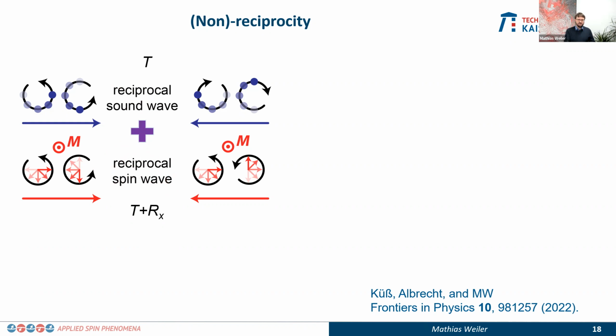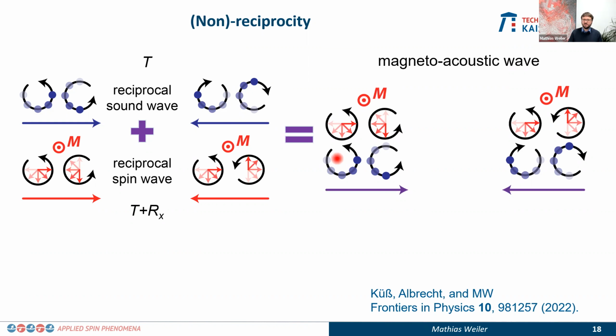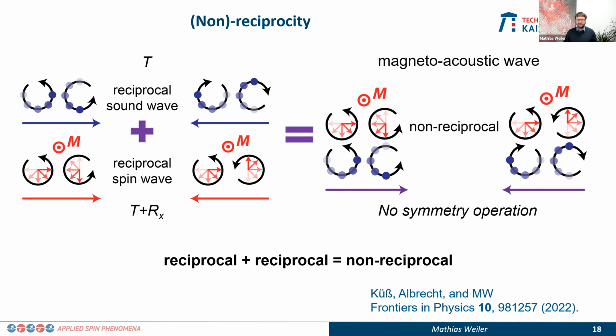But this reciprocity of these two waves, to go from counter-propagating waves to each other, requires a time reversal symmetry operation for sound and a time reversal plus rotation symmetry operation for spin. And that means if I combine these two waves, which is what we do in the magneto-acoustic wave, if you let them couple, then there is no symmetry operation anymore that can map the wave here on the left to its counter-propagating part. Okay? And that means we can indeed combine two reciprocal waves, a reciprocal sound wave and a reciprocal spin wave. We let them interact with each other, and then the magneto-acoustic wave that results can, by symmetry, be non-reciprocal. That doesn't mean that it has to be non-reciprocal, but it means it's allowed by symmetry.